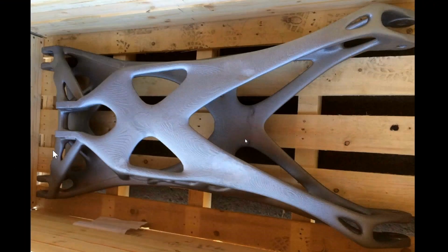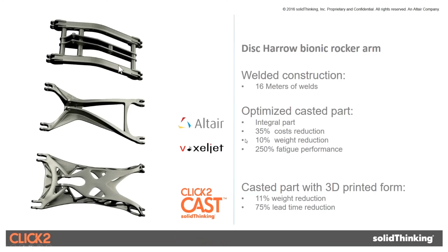And we actually did 2 different combinations of this. One was for traditional casting, if we wanted to do it without taking into account whether you can cast it traditionally. But we went ahead with a more radical shape on the bottom, which combines multiple components into one component, and it's impossible to cast this traditionally. So we 3D printed it, and if you look at it, the entire optimal casted part was 35% cost reduction.